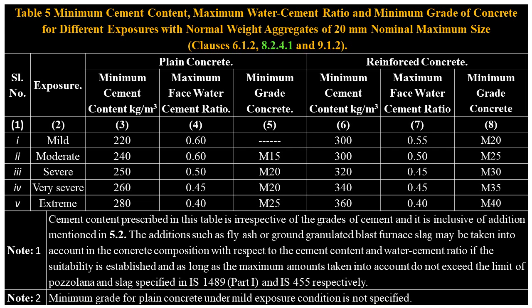Note 1. The cement content provided in this table is independent of cement grades and includes any additives mentioned in Clause 5.2. Additives such as fly ash or ground granulated blast furnace slag may be incorporated into the concrete mix regarding cement content and water-cement ratio, provided their suitability is confirmed. However, the total amount of additives must not exceed the limits specified in IS 1489, Part 1, for pozzolana and in IS 455 for slag. Note 2, it's worth noting that the minimum grade for plain concrete under mild exposure conditions is not specified.